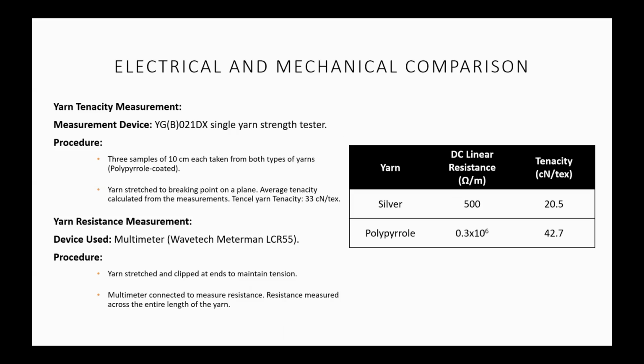But before we get to that result, let's look at the electrical and mechanical comparison. First we did the yarn tenacity measurement. Tenacity is the maximum amount of force required to break a yarn. In this case, the Tencel yarn itself would have like 33 centinewton per tex, but after the coating, the polypyrrole yarn has 42.7, so the coating increased the durability. And the silver yarn is rather brittle, which is 20.5.